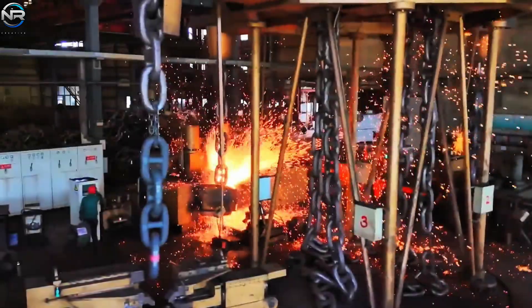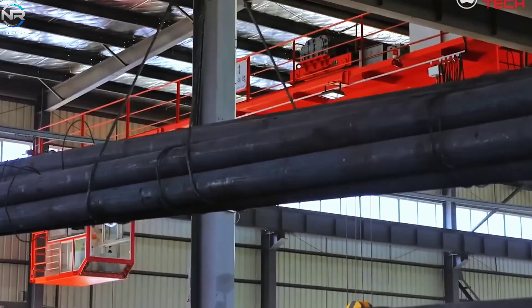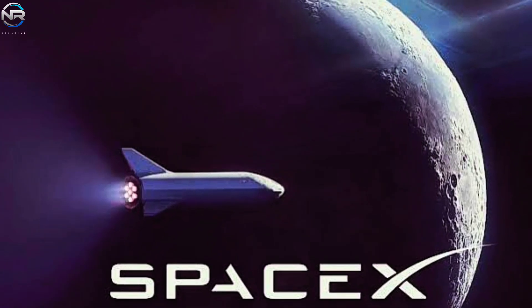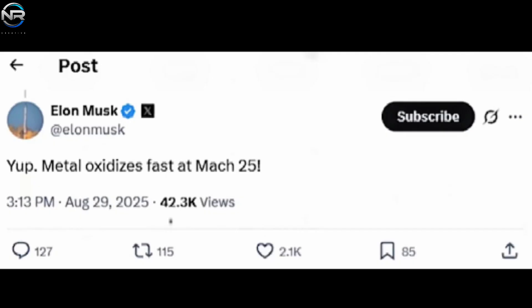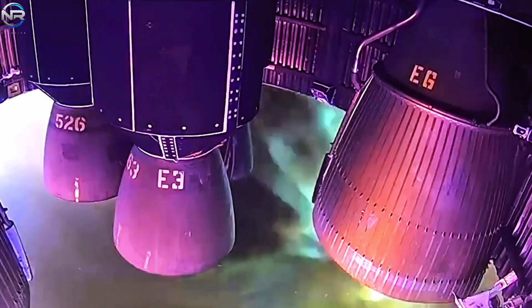From a physical perspective, metals like steel or iron alloys tend to oxidize when exposed to air without a protective coating. However, in space — especially in the vacuum of the universe — there is almost no oxygen or water vapor to react with these metals. This changes drastically upon re-entering Earth's atmosphere. At an altitude of about 110 kilometers, UV light from the sun breaks down oxygen molecules, creating highly reactive atomic oxygen. As Elon Musk noted, metals oxidize rapidly at Mach 25. When SpaceX installed metal tiles on Starship, the intense heat and plasma exposure during re-entry caused them to oxidize significantly faster.